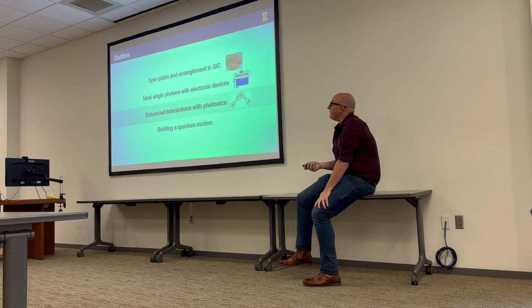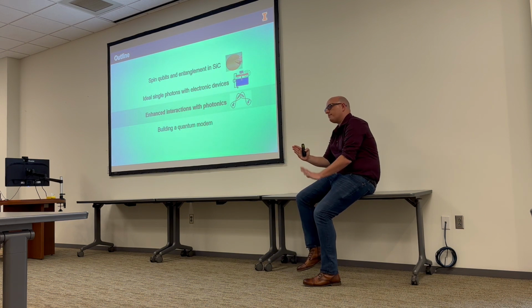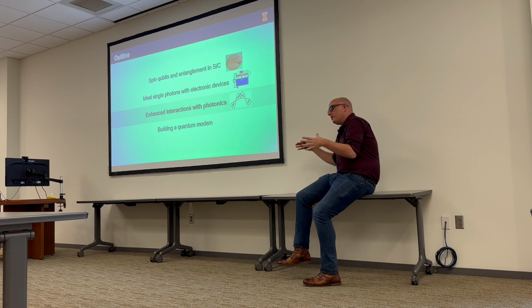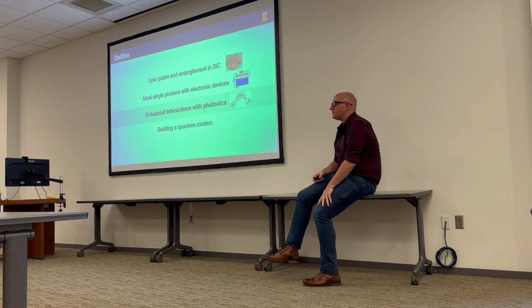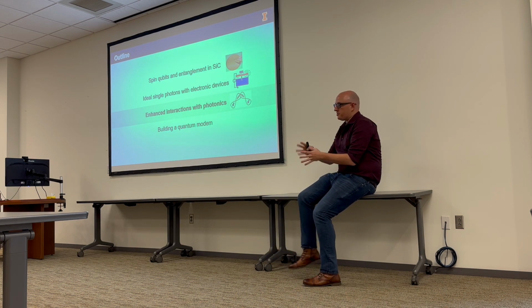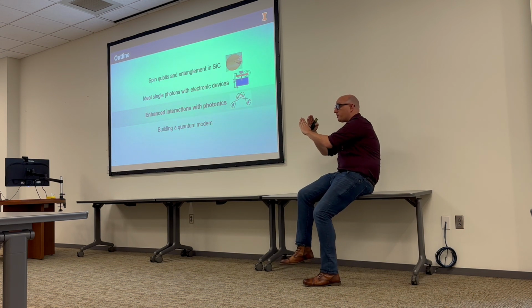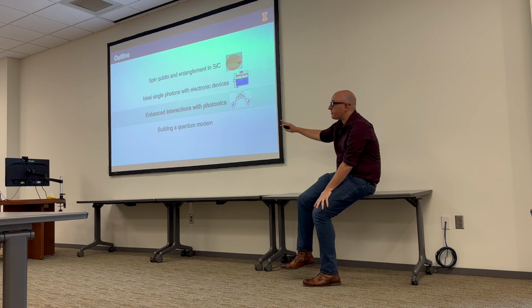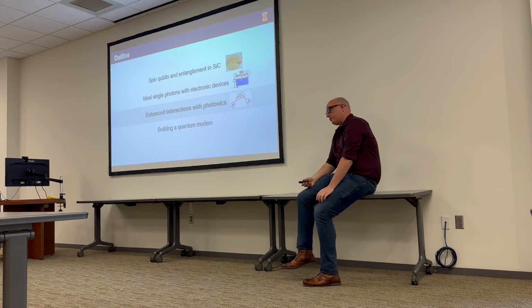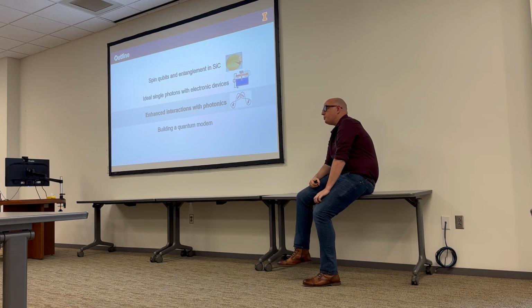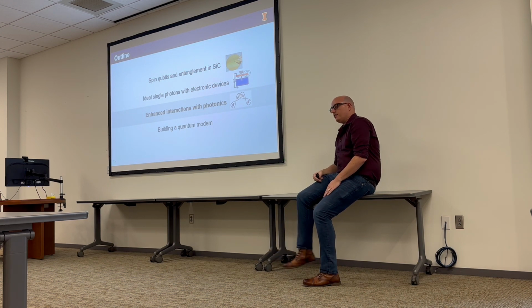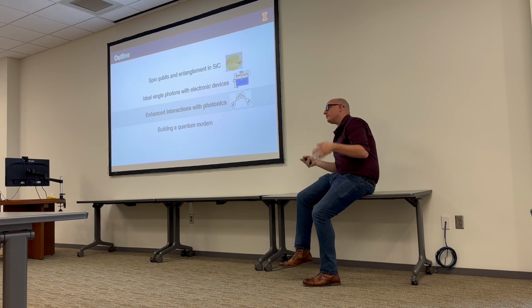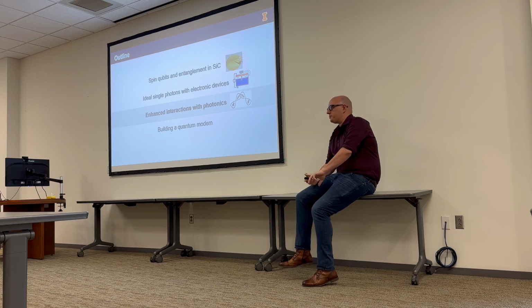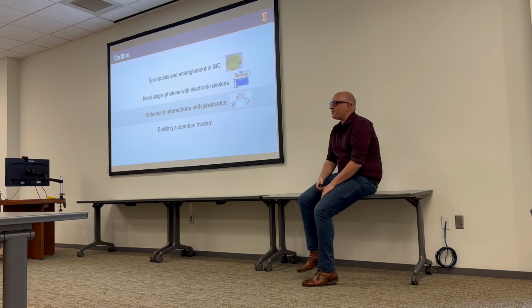In practice, what we do is we pump at one frequency, and then the emitter emits very broadly, and then we spectrally filter our pump from our emission. There's a spectral filtering that lets you do this, because otherwise your laser just blinds your detector. So we have a spectral trick that we play. Because as you said, you can do a cross-polarized thing to reject your pump. In this case, we do spectral filtering to reject our pump. You can also do time filtering, like you can give a little 1 nanosecond boost to your system. It goes to the excited state, and by the time it luminesces, your laser's turned off. You can also do tricks like that. Time, polarization, space, frequency. Those are your toolboxes for doing filtering.